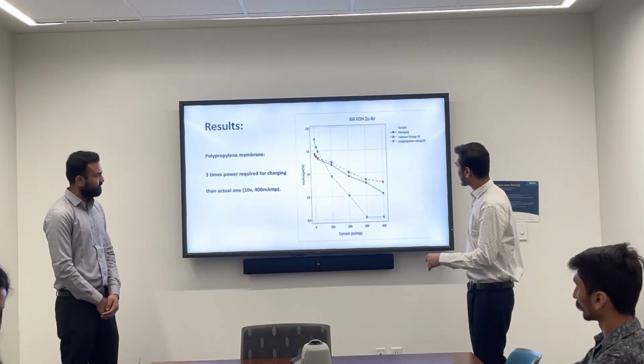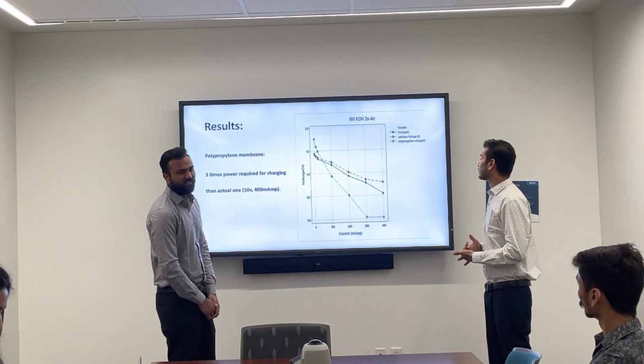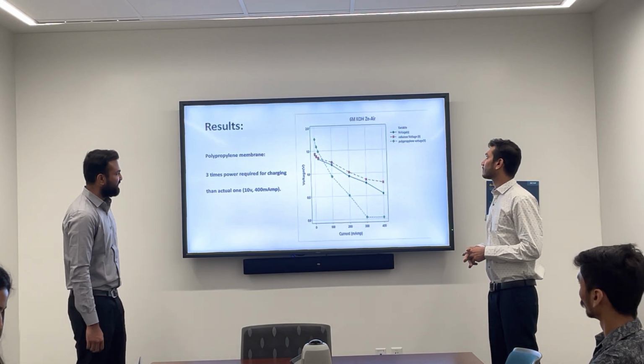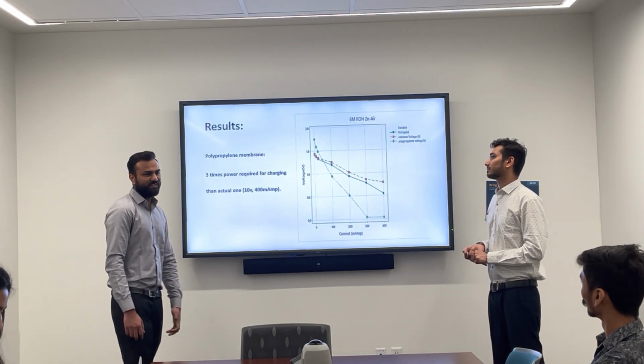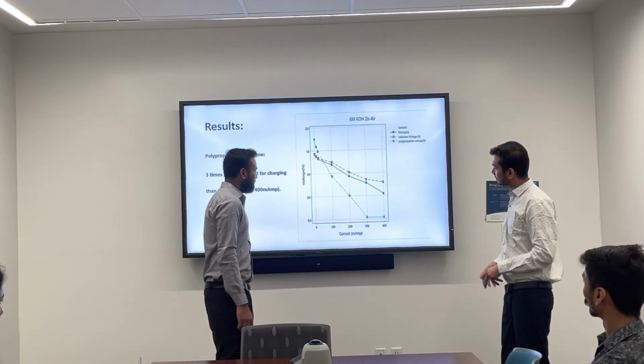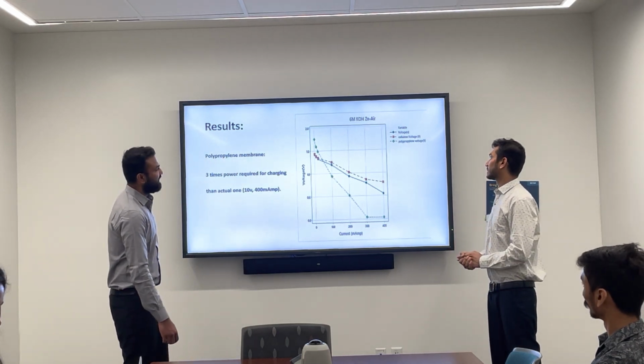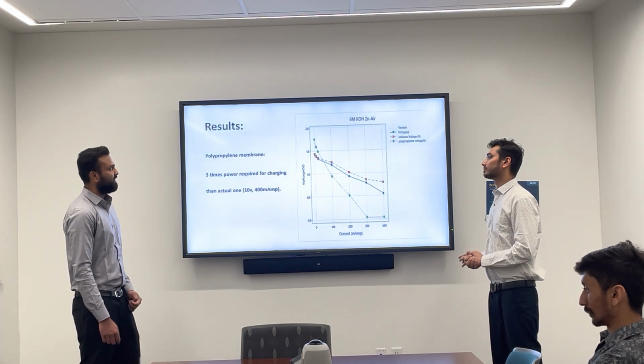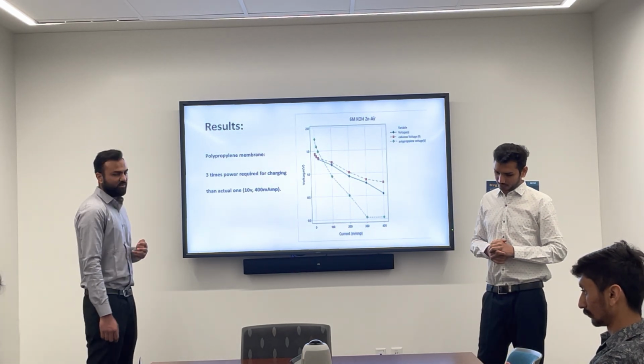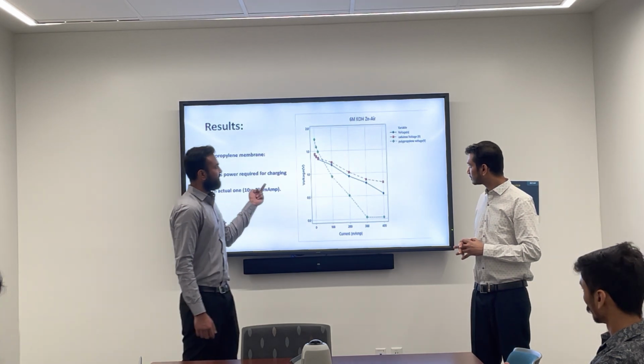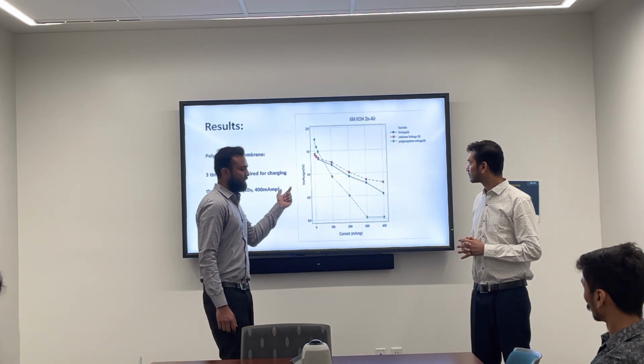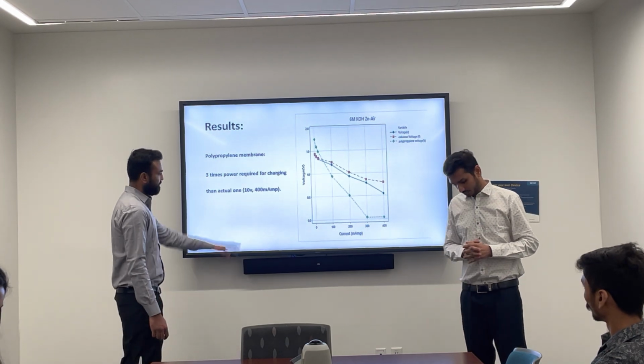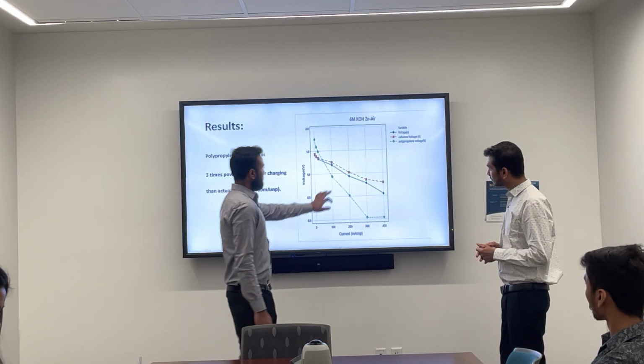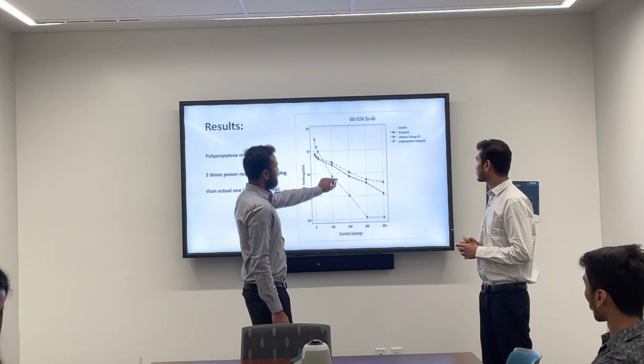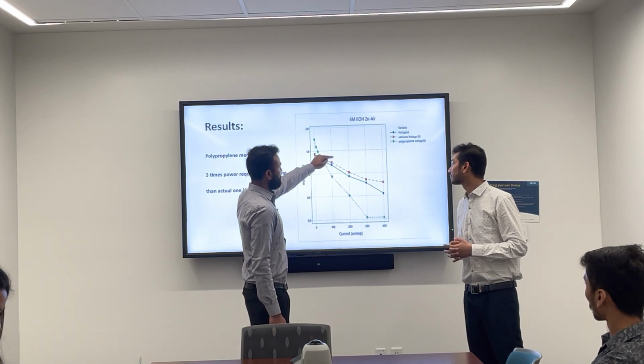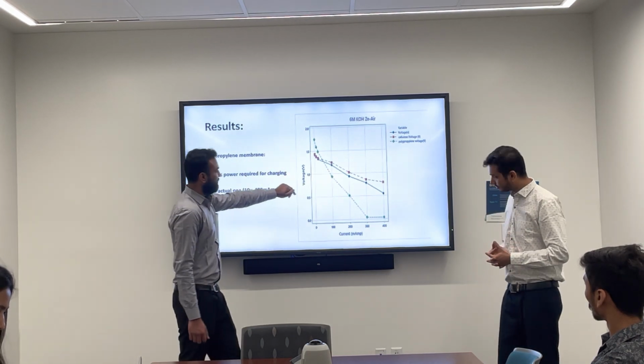Next slide. When it comes to the results, I can say that they are quite unsatisfying, but we are happy because something is better than nothing. So here is the power chart. As I said earlier, we performed and analyzed the battery in 2 molar, 4 molar and 6 molar, all 3 concentrations. What we got is that the battery performs better at 6 molar concentration among all concentrations. So here is the power chart of that performance. You can see the 3 trends. The blue one is without membrane, the red one is for cellulose, and the green one is for the polypropylene membrane.